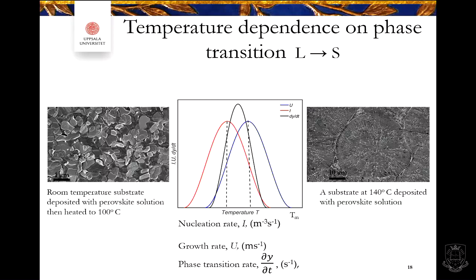It's sensitive to humidity. So the temperature here, as you can see, here we have the nucleation rate. Here we have the growth rate of crystals. So this goes back to classical nucleation theory. And then we have our phase transition, from liquid to solid, somewhere in between. So if you have a low temperature, you have more nuclei. That's why you have smaller grains. While at high temperatures, you have more crystal growth than actually nucleation. So that's why you also see these differences in the grains.